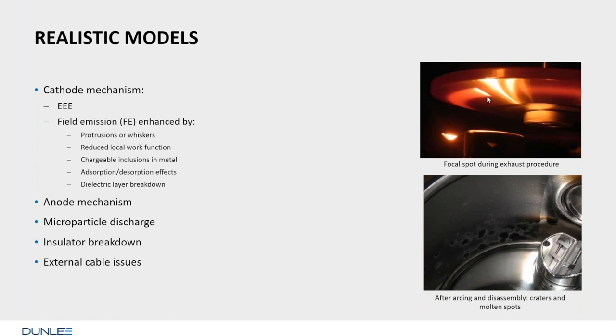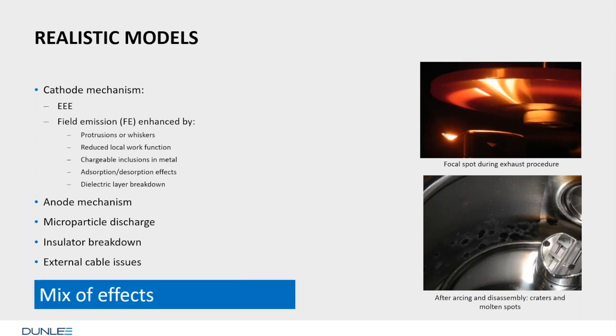I think it happens predominantly if these microparticles are charged and dielectric and not metal, but well chargeable, like ceramics dust or glass dust or whatever. But it can also be that metal particles do it. And then we have insulator breakdown and, of course, external cable issues. So this is a series of models which are most probable. It's a mixed effect often. Sometimes the tube starts with a cathode mechanism, then experiences also microparticles, because after a discharge, particles are released. An insulator may be deteriorating, and again, also from all these events and so on. So it may be a mix of effects even in a single tube.